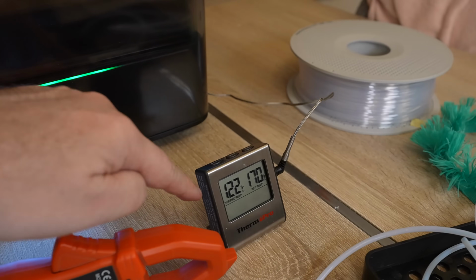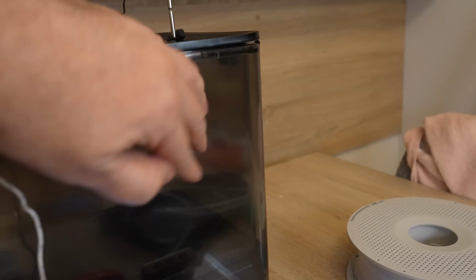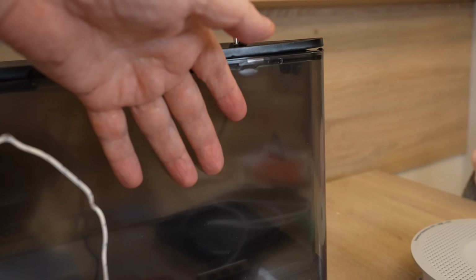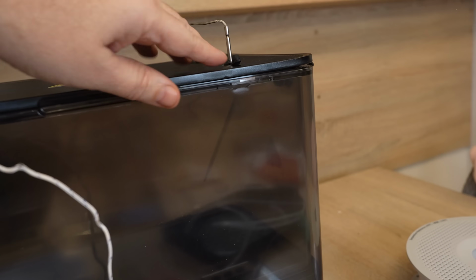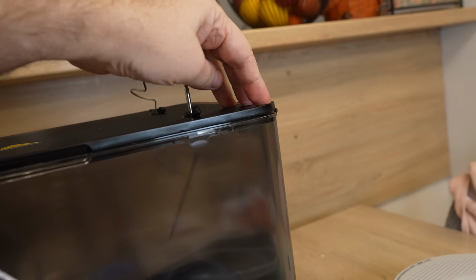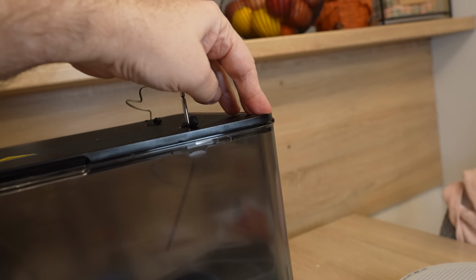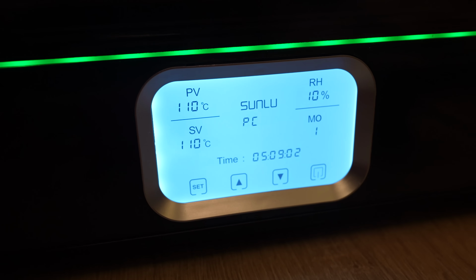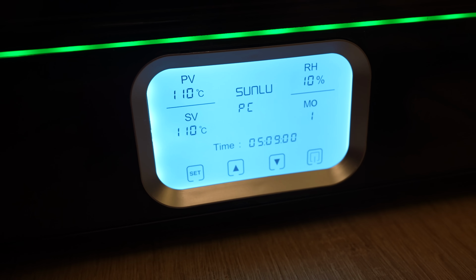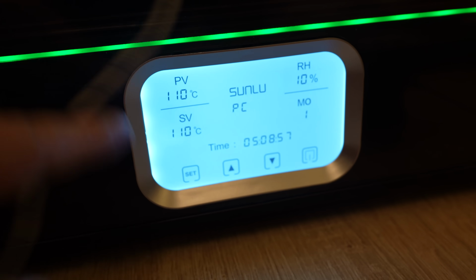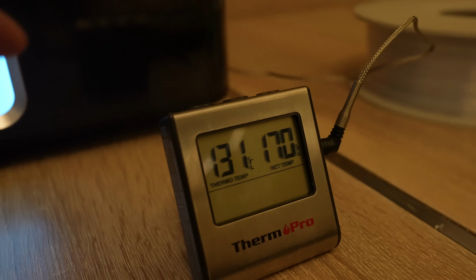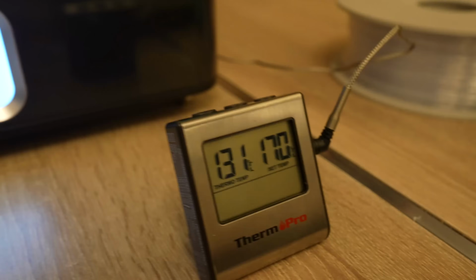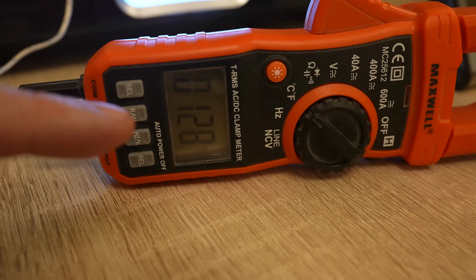Now, even if inside is 122 degrees Celsius, the wall is not hotter than, I don't know, maybe 60 degrees Celsius, so I can touch it without any problems. But this deforming really bothers me. Looks like after 15 minutes the temperature stabilized inside according to its own sensor, 110 degrees Celsius. According to mine, on the hot side it is 131 and on the other side 128 degrees Celsius, but I'm not even measuring exactly above the hot air, but a little bit closer where the spool would be placed.